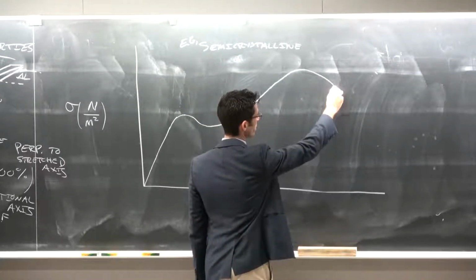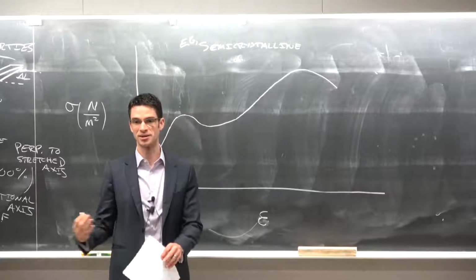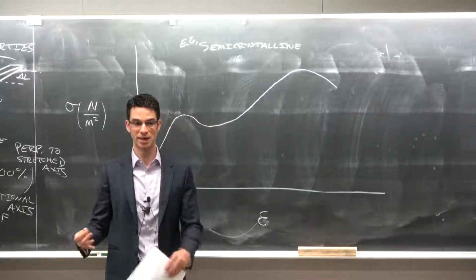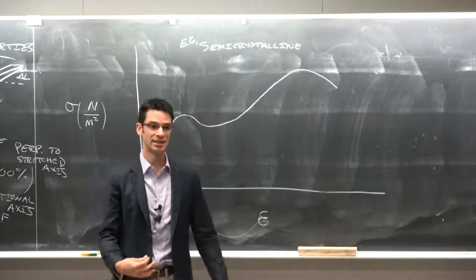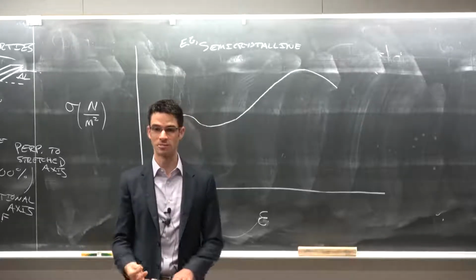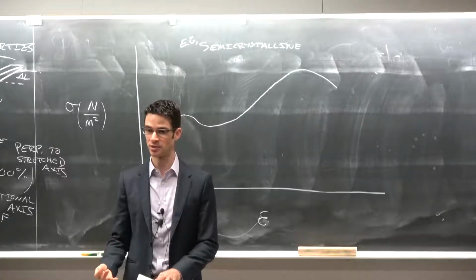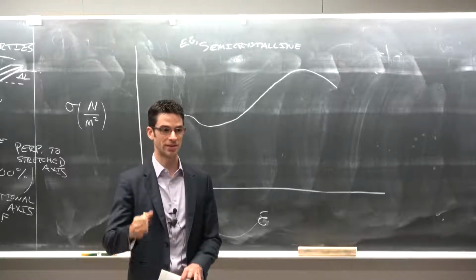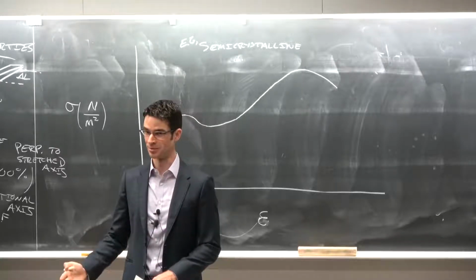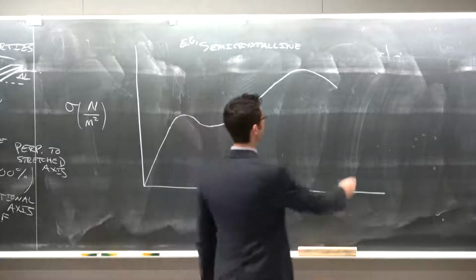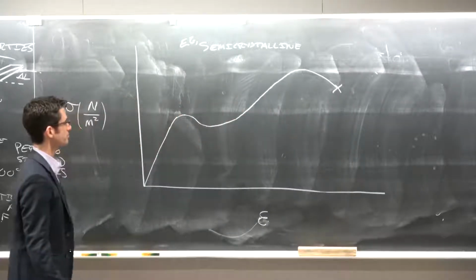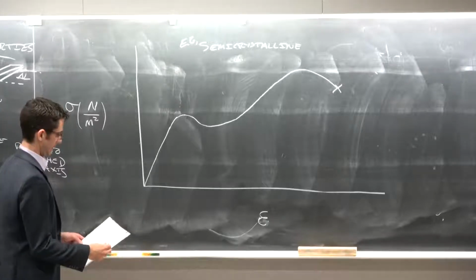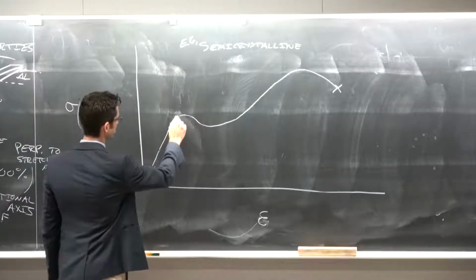And then it gets to a point where some combination of chains pulling out of the crystallites or past each other, or chain scission events, which happen in glassy polymers and purely cross-linked polymers, where you can't break the material without actually breaking covalent bonds in the solid, then it dies here. Okay, let's name some of the key features here.